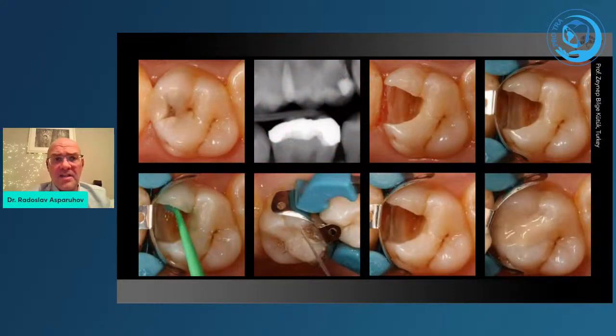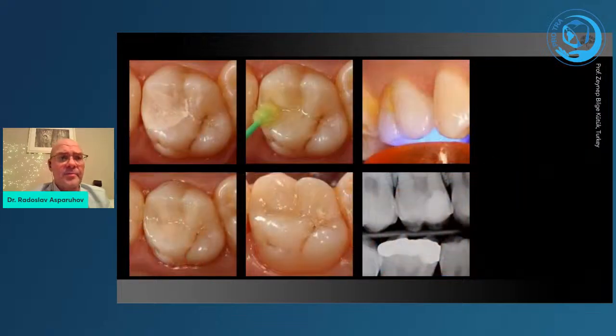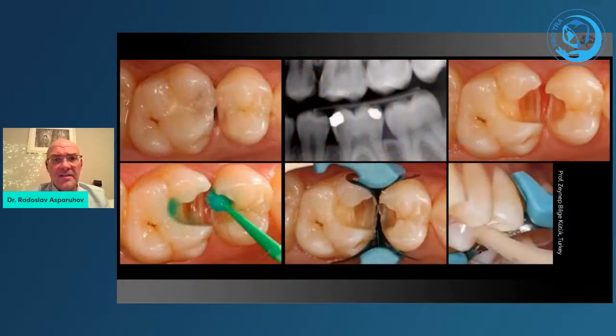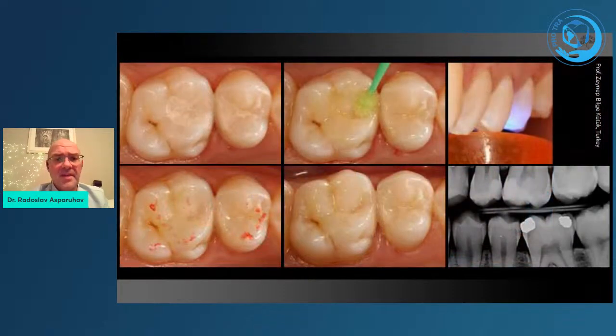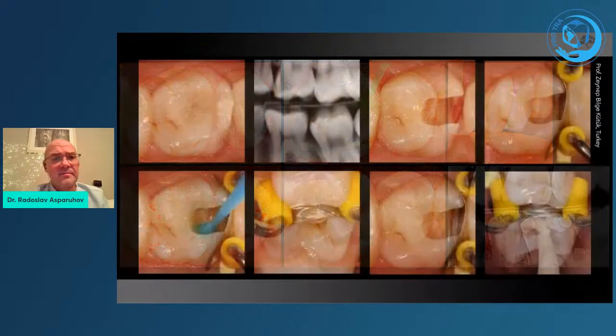And another case that is similar. As you can see, again, no rubber dam, removal of only infected tissues, rinsing after cavity conditioner, applying the glass hybrid in bulk, adjustment, and then covering of the occlusal surface with the resin coating, which is afterwards light cured. And again, you can judge the aesthetics. And a third case, similar to this one, same procedure and more or less the same result.